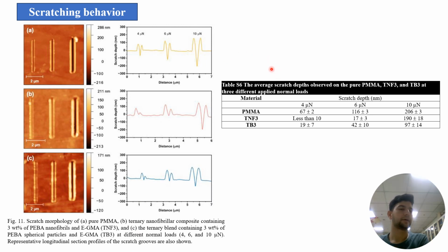I think this is the second last slide. Scratching behavior. So we check the scratching behavior of the polymer. In figure 11, it shows the scratch morphology and longitudinal section profile of the scratch groove after elastic recovery for different normal loads, 4, 6 and 10 micronewton, on pure PMMA. It is for pure PMMA.